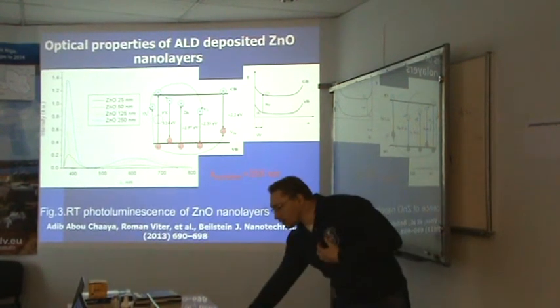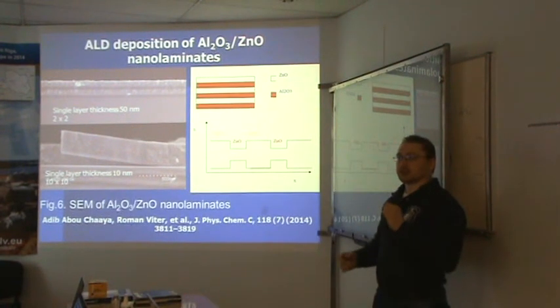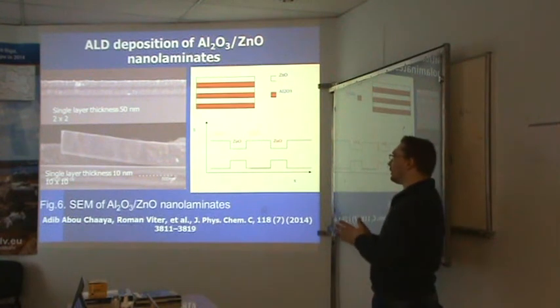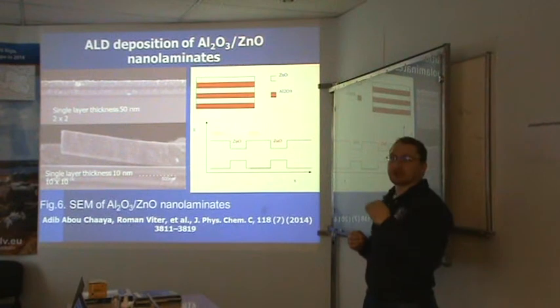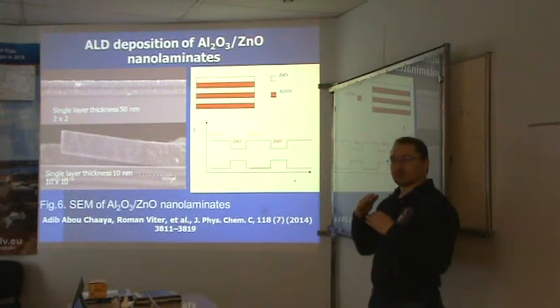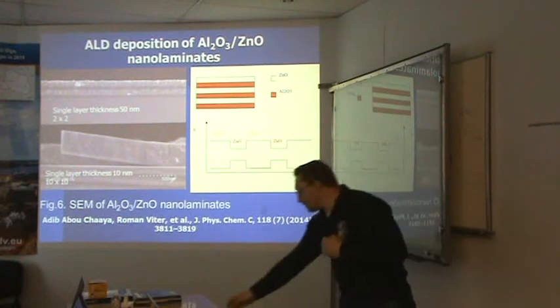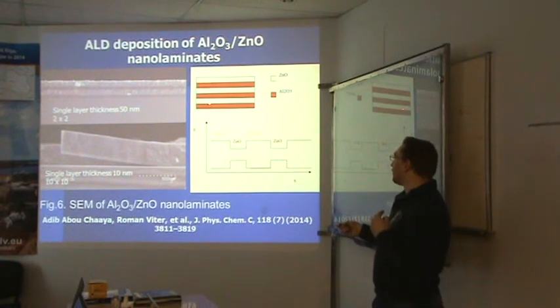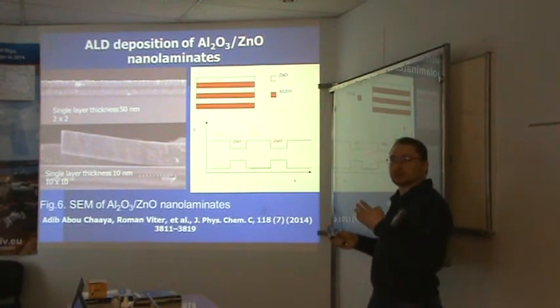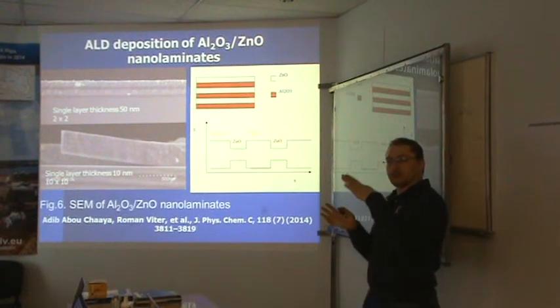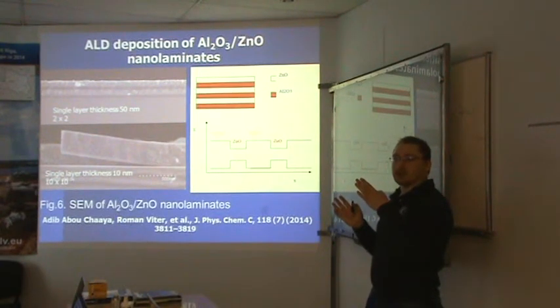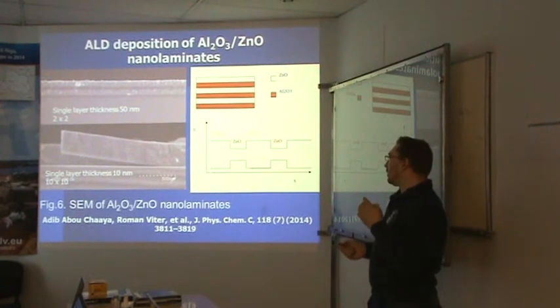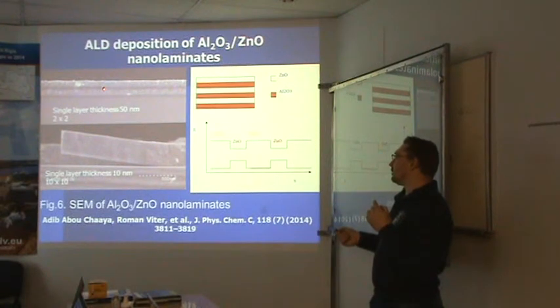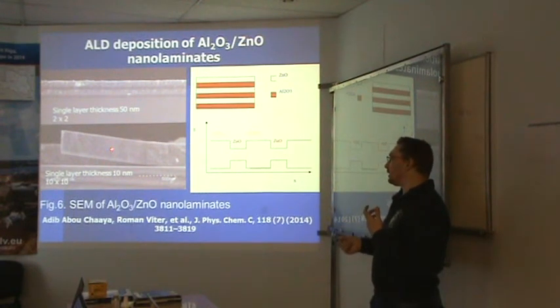The next step was to tailor the properties of these materials, and we deposited composite materials called nanolaminates. They consisted of two types of materials: aluminum oxide and zinc oxide. Firstly, aluminum oxide was deposited, and then zinc oxide was grown on top of it. These cycles were repeated to reach a constant thickness of the whole construction of 200 nanometers, and we changed the thickness of the single layer. Here you can see the SEM of this nanostructure with a 50 nanometer single layer, and here 10 nanometer single layer.